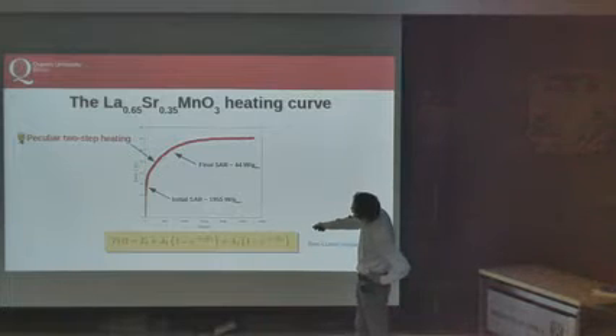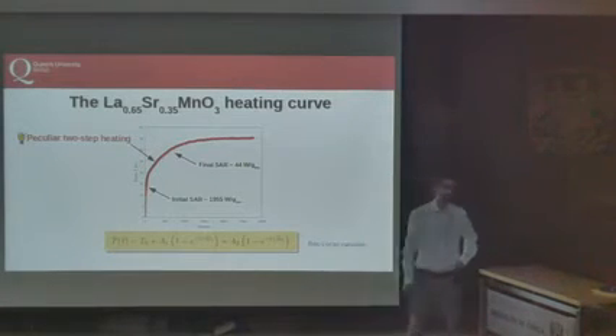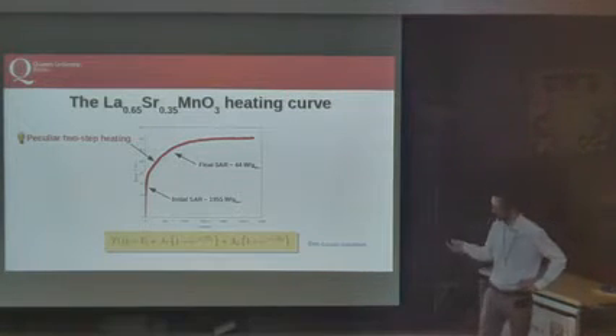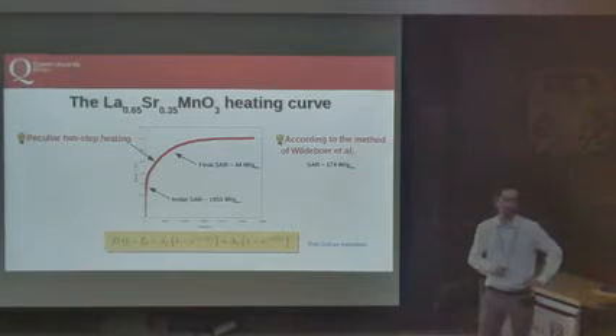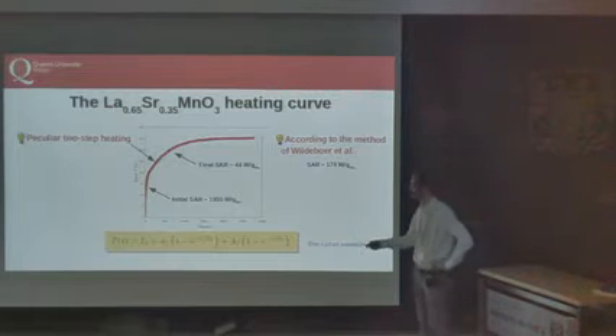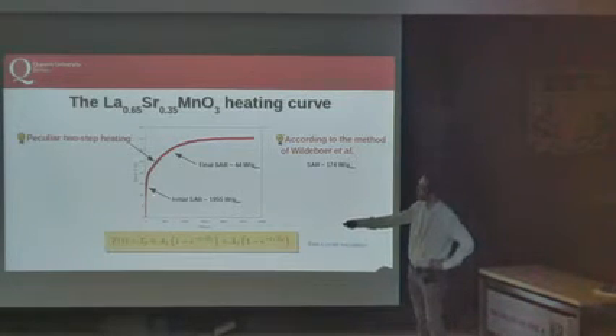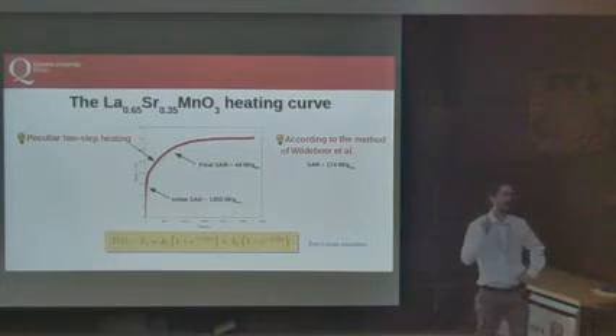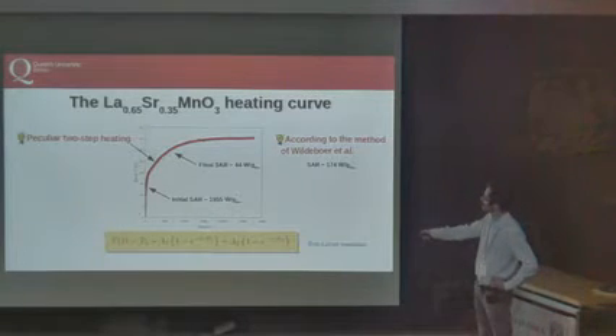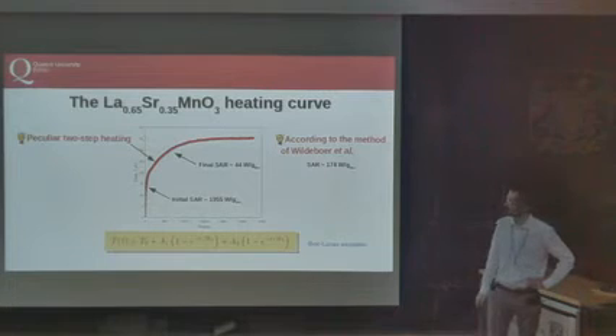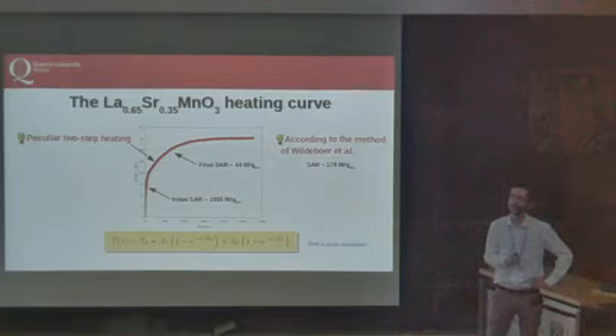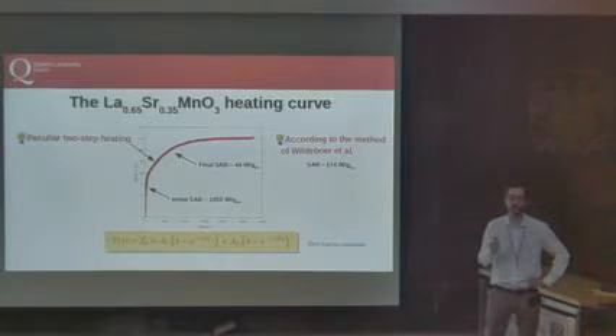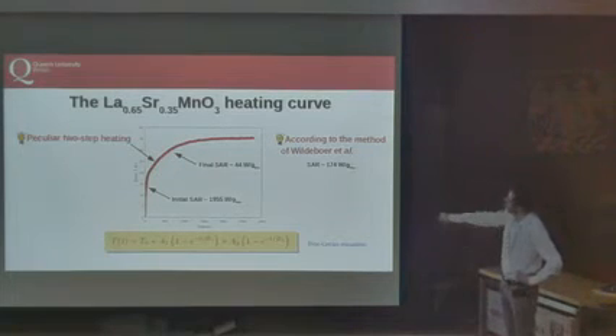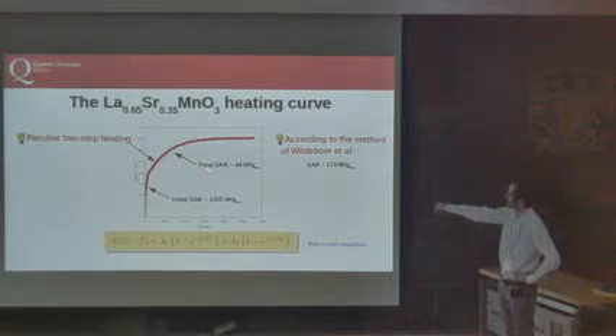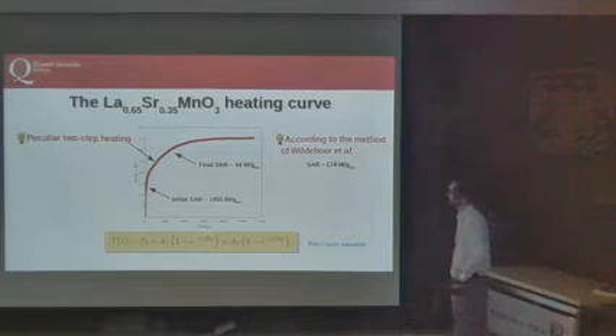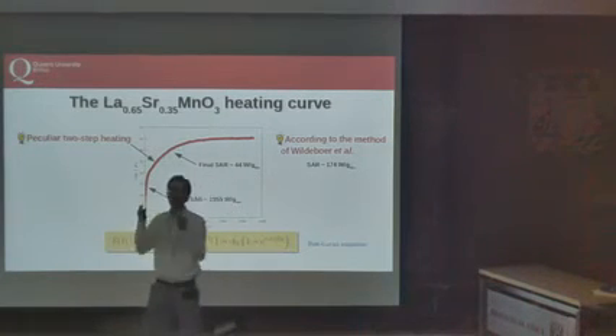The fits, you should probably not even see the black line because it's very good. How can we interpret this? Well, we go to the experimental articles, and we see that after processing of this quantity, we can associate to the first part of the slope a very, very high SAR, like almost 2,000 watts per gram of manganese. And probably, I might have flashed this information before, we have 10 milligrams of nanoparticles per each milliliter of solution, if I remember correctly. While the second part of this Box-Lucas equation gives us 44 watts per gram of manganese, so a much lower heating power.